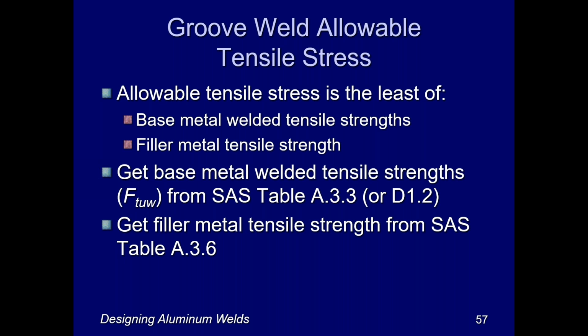Now, the allowable tensile stress is the other part of the equation, once we've got the size of the weld and the area of the weld. And the allowable tensile stress is the least of the base metal welded tensile strengths and the filler metal tensile strength. We get those base metal welded tensile strengths from the Specification for Aluminum Structures table or the D1.2 table, and we can get the filler metal strengths only from the Specification for Aluminum Structures.